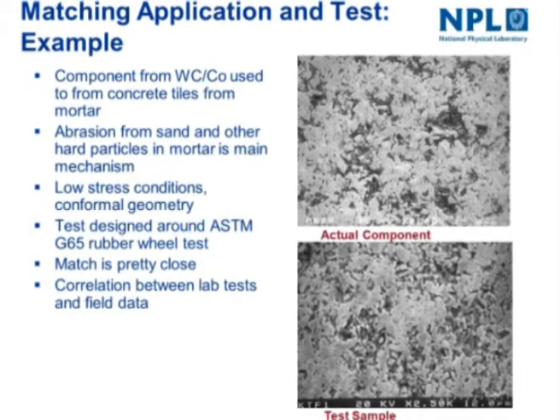We realized it was a low stress set of conditions, conformal geometry. We looked at what's called the ASTM G65 rubber wheel test. We modified that somewhat. One of the main things we did was we changed the pH of the fluid that we used in that test. We also modified it so that you could carry out the test wet. For those that know, that's normally a dry test, but we had it wet.